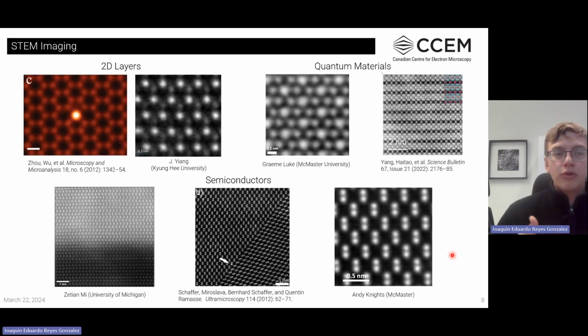Well, the important thing is that we're using this for STEM and we're using it for EELS, for STEM and spectroscopy. Now, the STEM is very good because it's giving us this nanoscale information, atomic scale information. But if we're working at very low accelerating voltages, then we are getting these very high inelastic scattering cross sections, meaning that we're going to essentially boost the strength of our EELS signals.